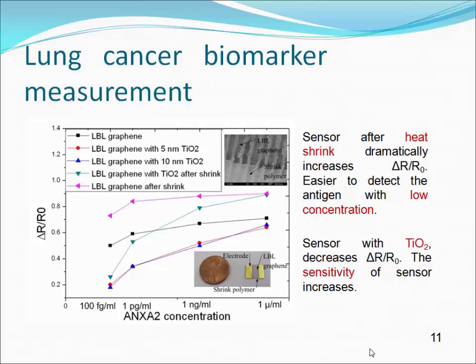But we find another interesting phenomenon. The signal doesn't reduce too much in high concentration. We still need to study the reason, find out the reason. But as a result, the slope of this curve increases. So from the definition of sensitivity, our sensor has higher sensitivity after adding titanium oxide nanoparticles as a result.